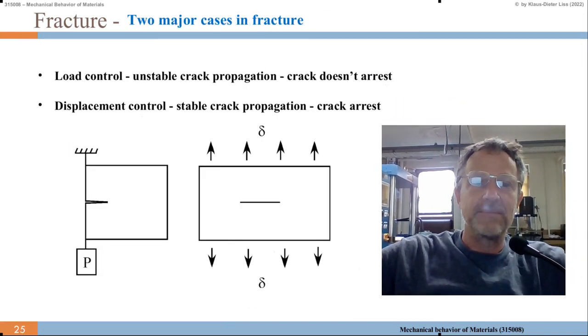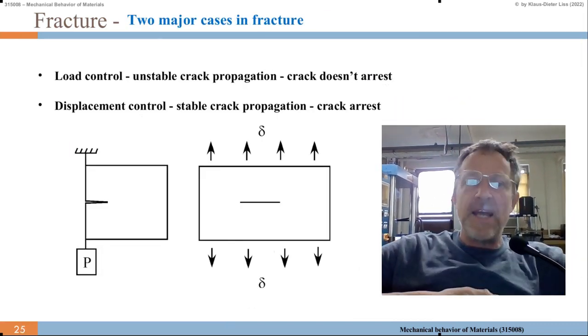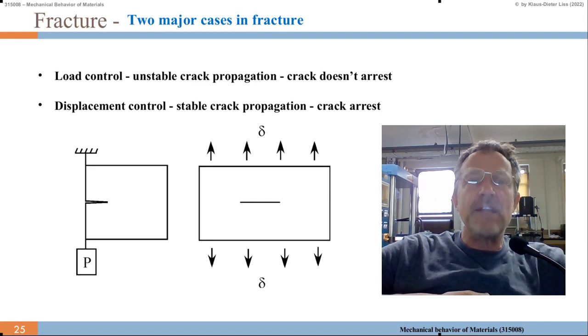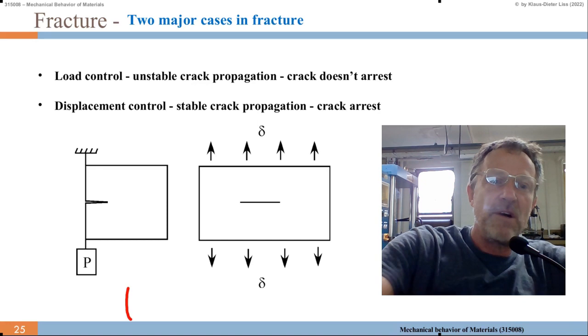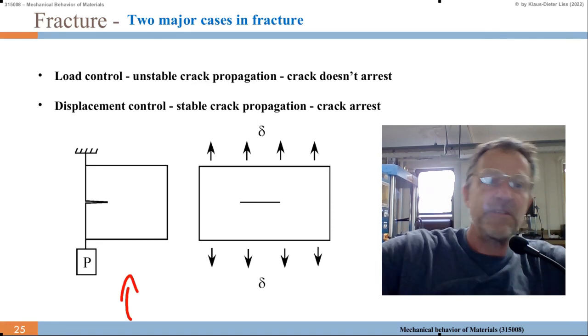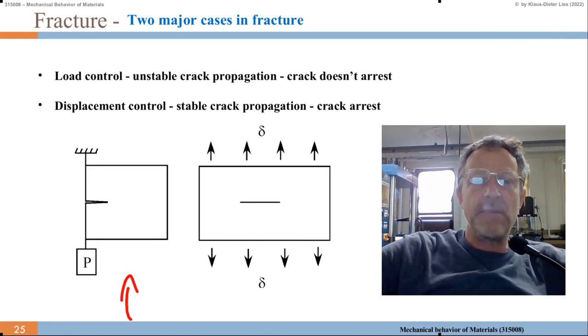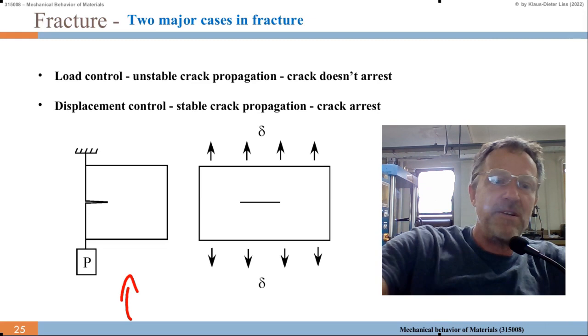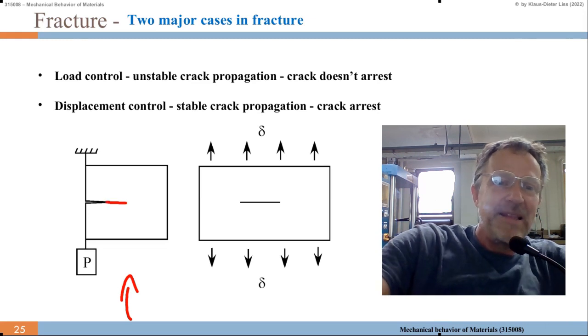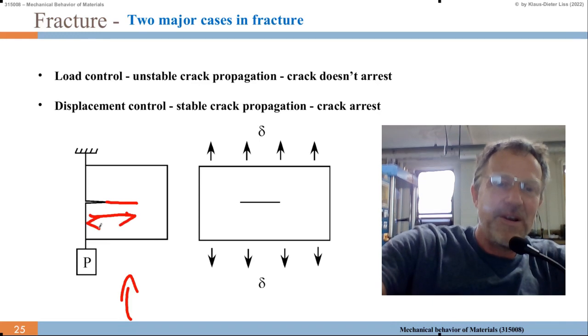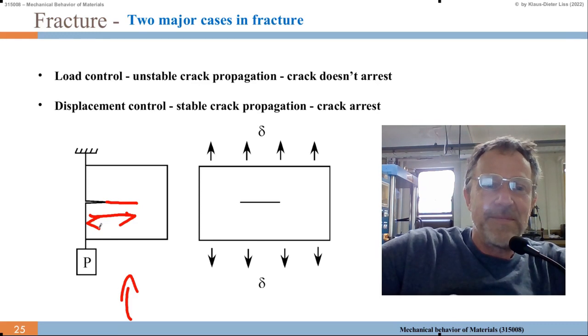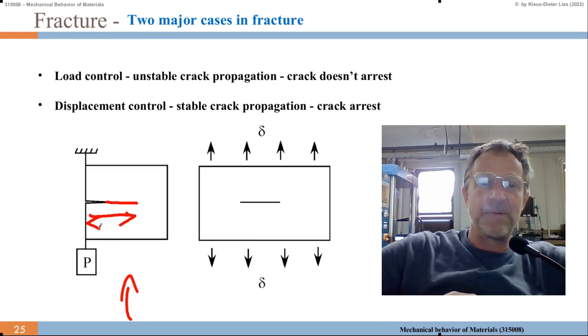So there are two major cases in fracture. The one is load control, which we show like the figure to the left. This is the unstable crack propagation. Imagine you have this form here - when the crack becomes longer, you have a longer lever arm, A, to the crack tip, so you put more torque onto the crack tip. That means the stress becomes higher.